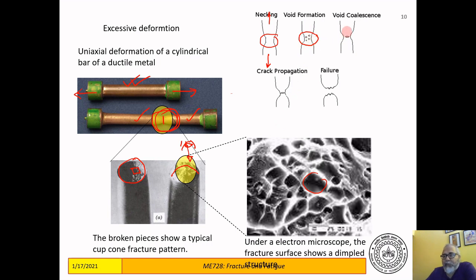Then some of these voids might coalesce to form a bigger defect, and then this bigger defect, if it's big enough, can grow, can propagate. That's where fracture mechanics comes in and causes failure here. So this is the initial defect from which fracture mechanics would start to operate, but this defect comes about through the formation of voids: void nucleation, then void growth, then voids coalesce, and finally a large enough coalesced void would propagate to form a crack which will lead to failure.